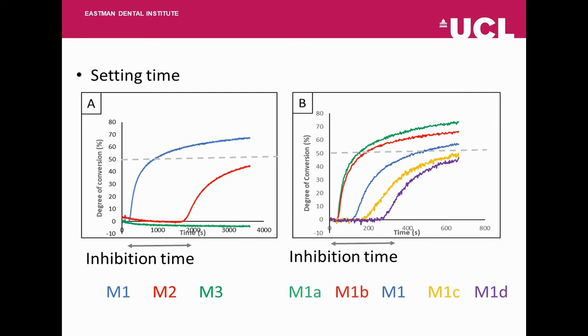an hour, and the decrease in initiator activity delays the monomer conversion by approximately 30 minutes. Hence, the final conversion for formulation M2 is not really representative of the composite because it's still reacting. And then we can see with M3 there is no conversion, confirming that these levels are obviously very low and far too low for the formulation.